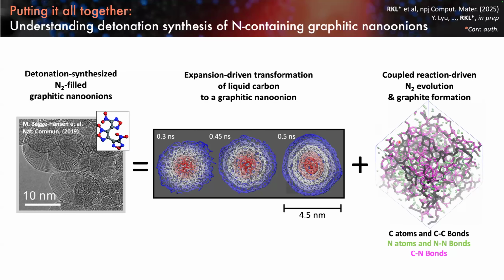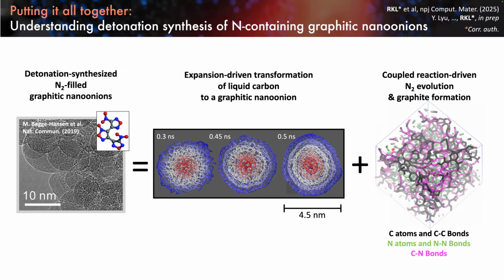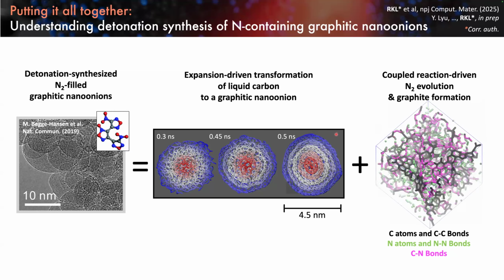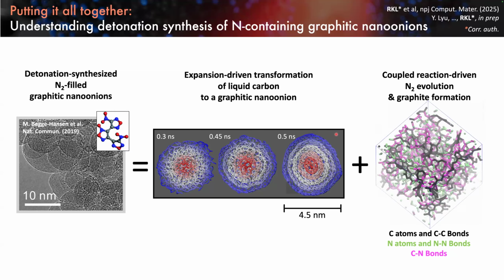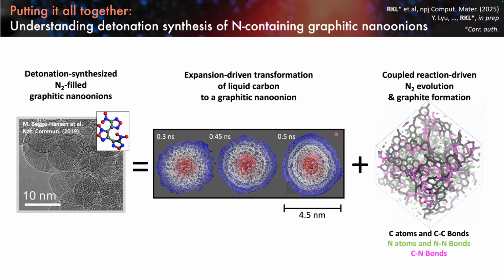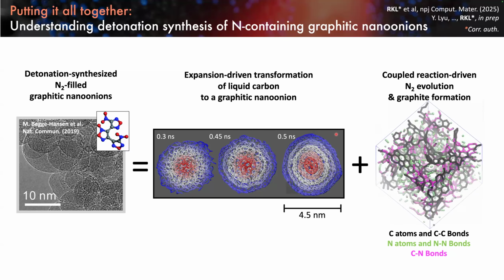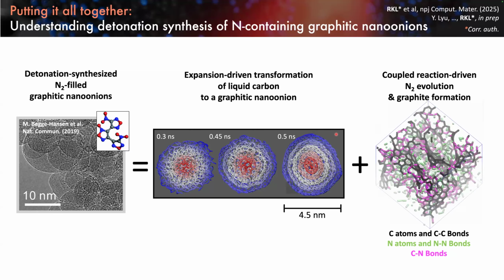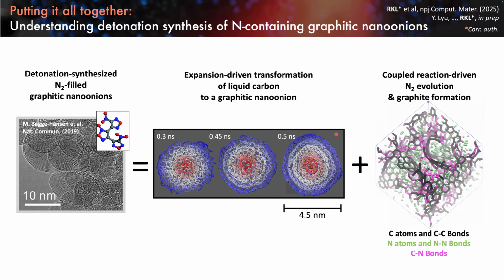So if you take these two images together, the snapshot and the movie, this suggests the following: when these nanoparticles are formed in the liquid state, they likely have nitrogen in them, because our simulations have suggested that nitrogen is very soluble in carbon.